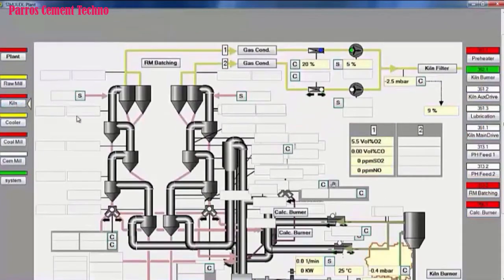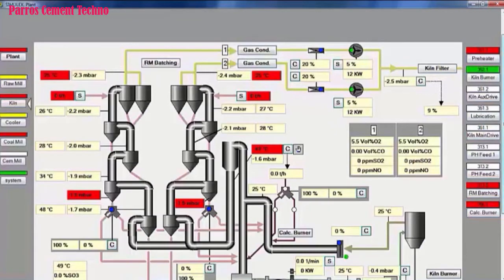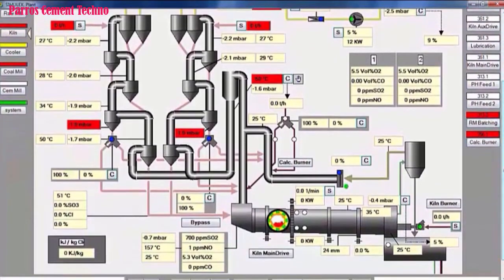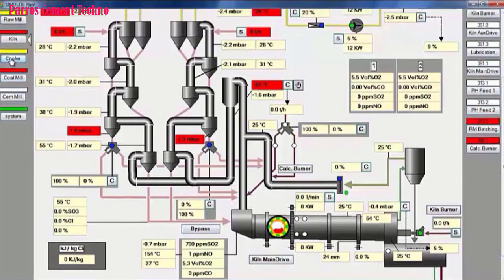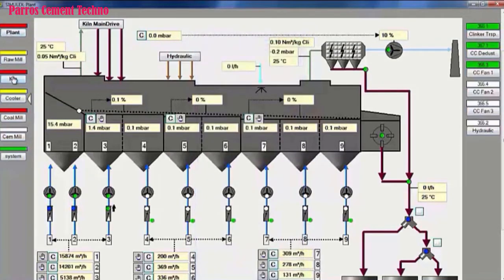After entering the fuel oil in the main burner, we observe the parameters on the kiln display, especially O2, CO, the temperature in the sintering zone, and in the kiln inlet. We observe here that the temperature in the sintering zone should be higher than the temperature in the kiln inlet. But currently the temperature is higher in the kiln inlet. This means that the pull of the preheater ID fan is too fast. Let's try to reduce it using the addition of air from the cooler. We add 10% each and we observe whether the heating temperature can last in the kiln and not be pulled quickly to the preheater system.